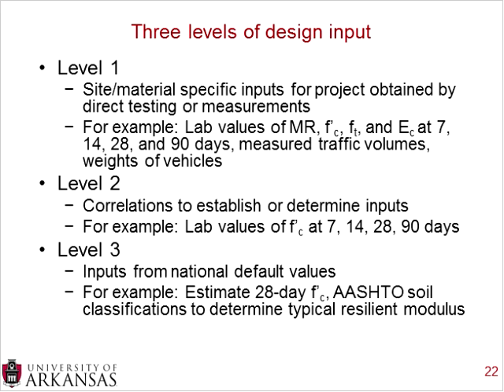However, they have provided 2 more levels, where, for example, level 2 is where you use correlations to establish or determine inputs. So for example, you only need the lab values of the compressive strength at 7, 14, 28, and 90 days. And the program DARWin-ME will automatically give you correlated values for the MR, F_t, and E_c. So you've decreased your testing significantly, by probably over 75%, by using just the compressive strength. However, then you're moving into using correlations established by other groups, maybe other climates, other materials, so there's some risk associated with that as well.